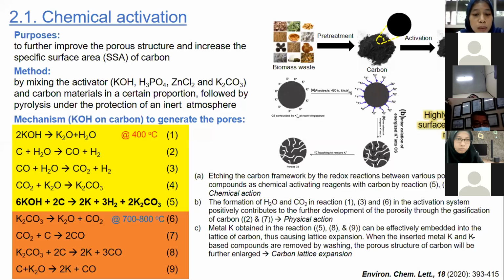The common activators are potassium hydroxide or KOH, phosphoric acid, zinc chloride, and also potassium carbonate. And among them, KOH is the most popular chemical activator that is generally used. The activation mechanism of KOH on carbon consists of several simultaneous reactions, like the following reaction.